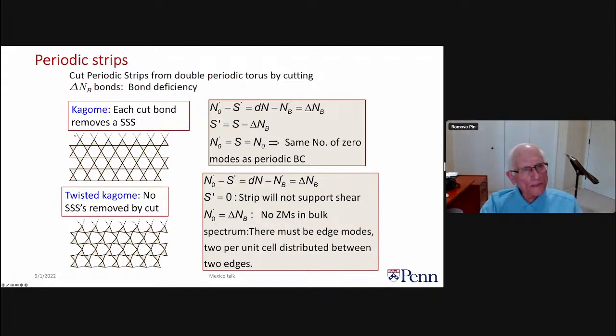And what has happened then? I have removed 2 bonds per unit cell. Since I've broken the contact between this point and the opposite point at the end, I've destroyed the efficacy of this straight line to support self-stress. So we've removed 2 bonds per unit cell, and we have removed in the process 2 states of self-stress, the ones that go like that. So that tells us that the change in the number of bonds is equal to the change in the number of states of self-stress. So this is the Maxwell-Calladine relation for the new system. The new N0 minus the new state of self-stress is equal to dN minus NB prime. And NB prime is NB minus delta NB, so that N0 prime minus S prime is equal to delta NB.